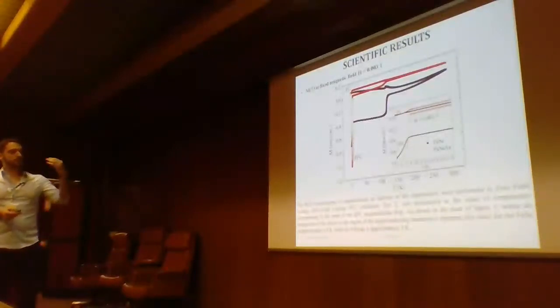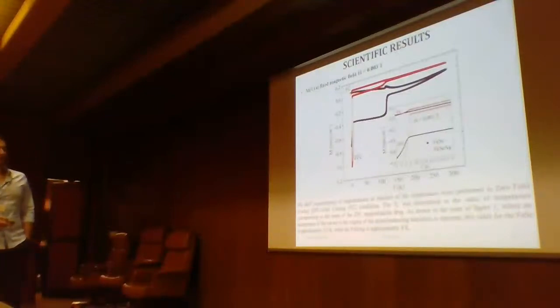From these measurements, the first characteristic that you can observe is the determination of the critical temperature. In particular, you can see that for the undoped sample, it is around 8.5 Kelvin, taken as the onset of the zero field cooling curve, that is this one for the black, and this one for the red, that is the silver doped sample. And for the silver doped sample, it is approximately 9 Kelvin. So you have an improvement of this critical temperature of about half a Kelvin.